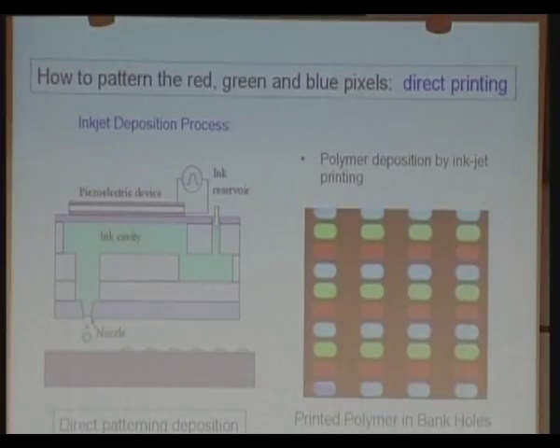What we have done is to formulate soluble polymers, different polymers that will emit red, green, or blue, depending on their chemical composition, and arrange that we can print them using the same print heads that one would have in a home printer. So on the left is an image actually of an Epson printhead. We've worked a lot with Epson. On the right is a blown-up image. The repeat distance here is about one-third of a millimeter of green, red, and blue subpixels, which have been obtained by printing the polymer, which is then being electrically excited in the light-emitting diode.